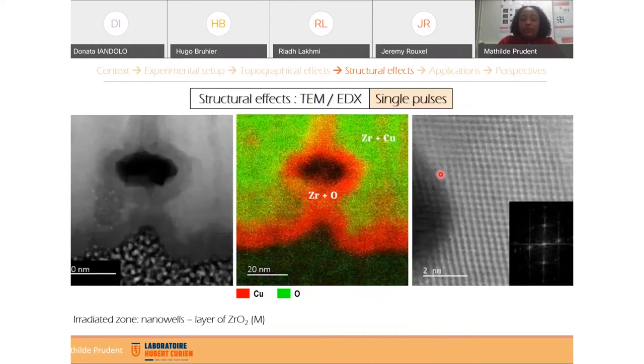We also realized some EDX mapping, but now in the nanowell zone. And now you can see that around the nanowells, we also have a zone with a high concentration of zirconium and oxygen, and also in the surface of the sample. But now this zone is crystallized, and after different analysis on the atomic plane here, we found that we have a zirconia in monoclinic structures here.